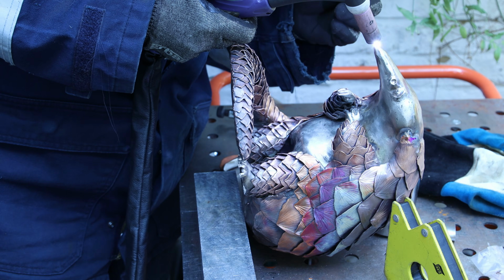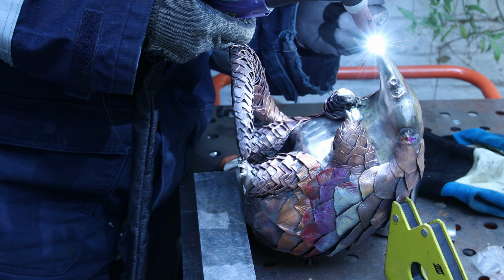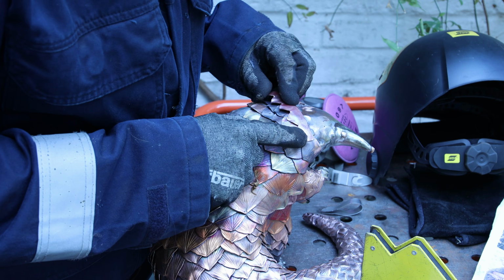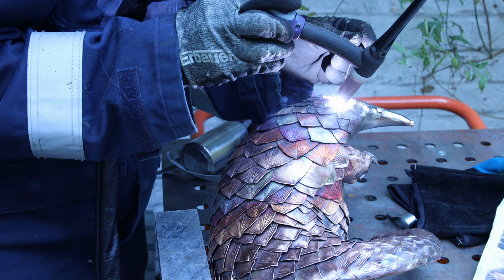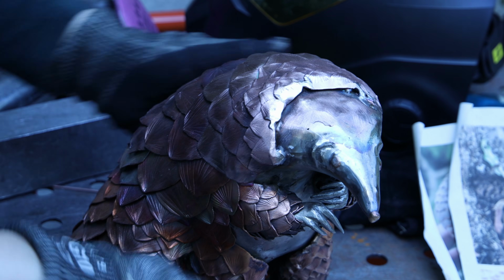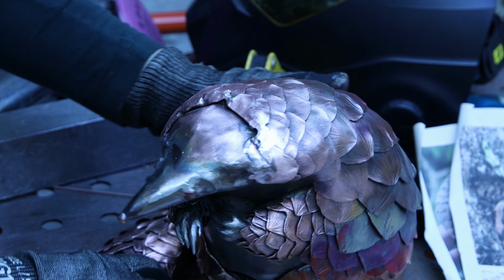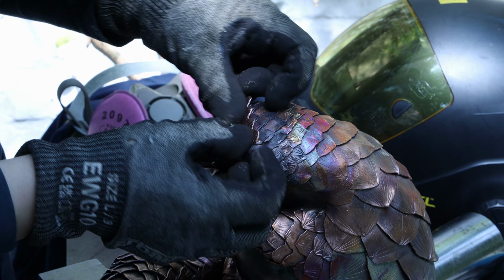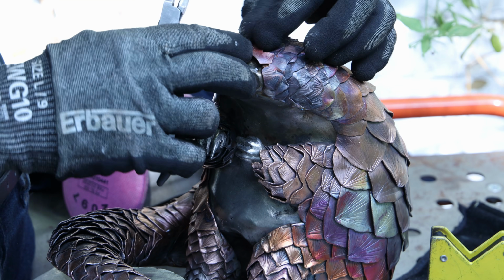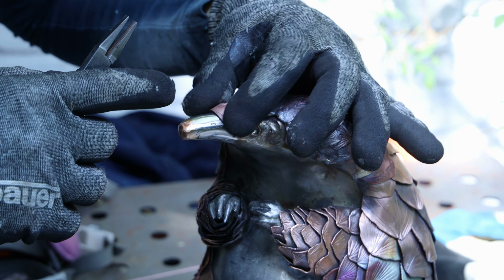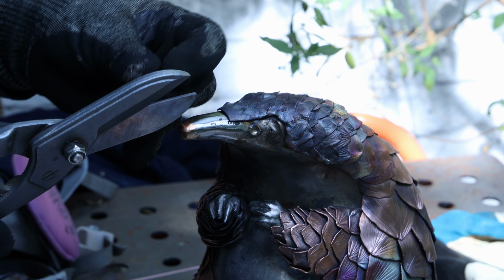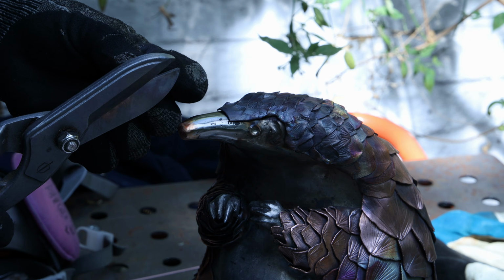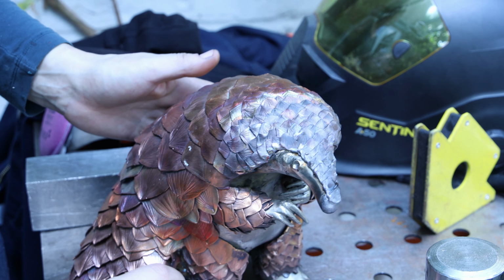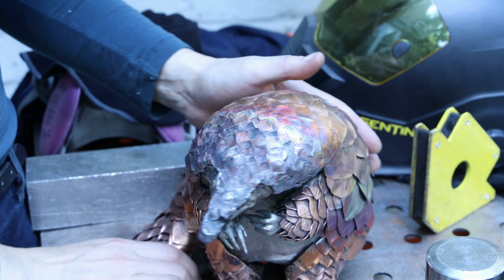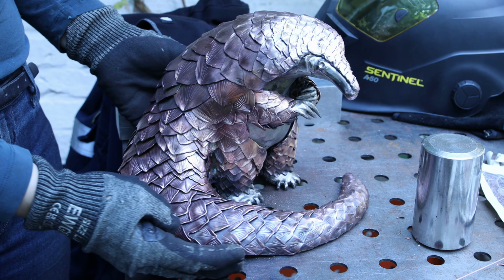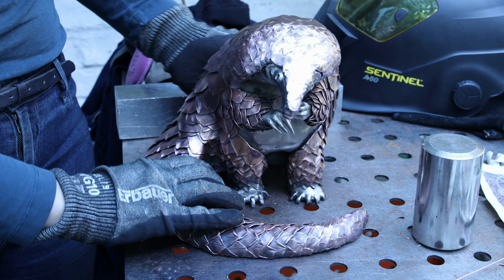I've added a muzzle with my TIG and pure copper rods. And I kept adding more and more scale, getting smaller each time, and it was getting trickier and more challenging to weld without melting it. I got closer and closer towards the head, and the scales were getting thinner, up to the point that I barely had 1 or 2 scales per line, which took a lot of patience and adjustment before I was able to weld it. And this is what it looked like when it's all welded, and it looks a bit better after some wire brushing, but at that point it still needed a lot of touch-up.